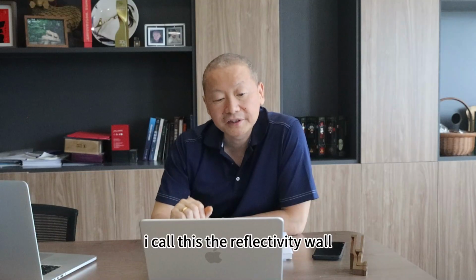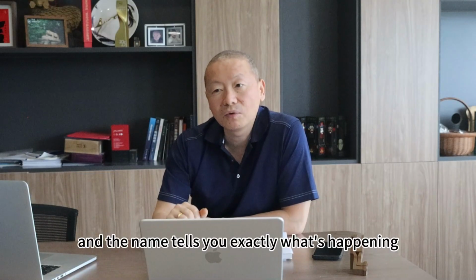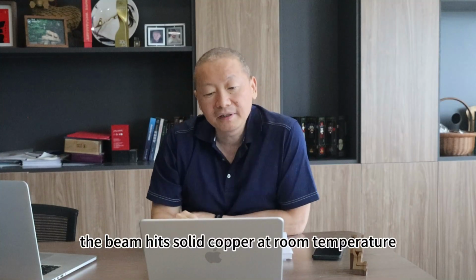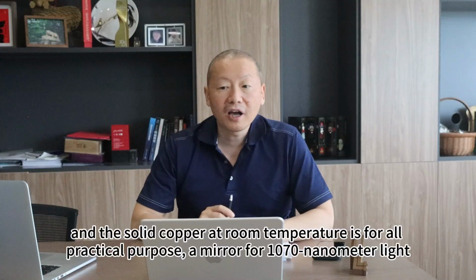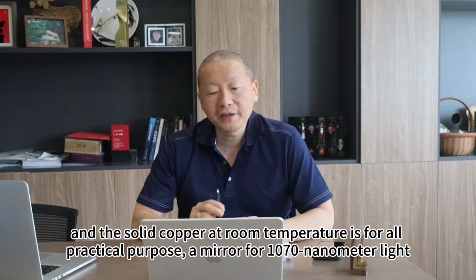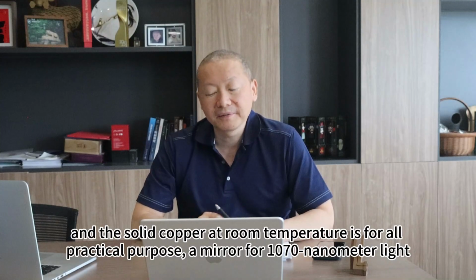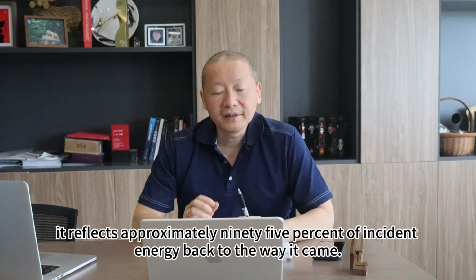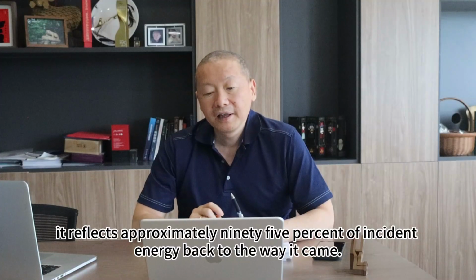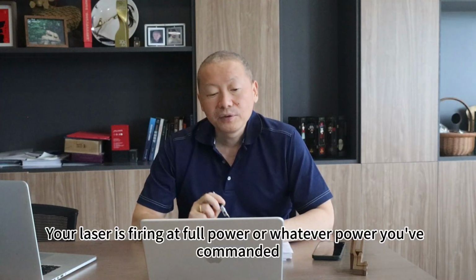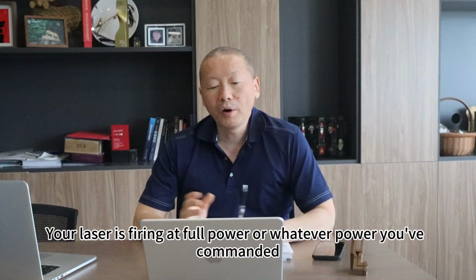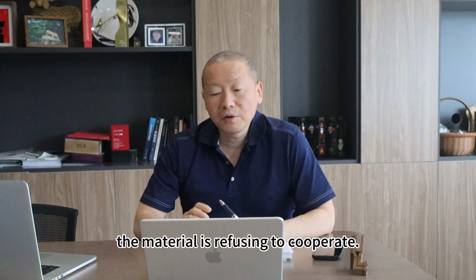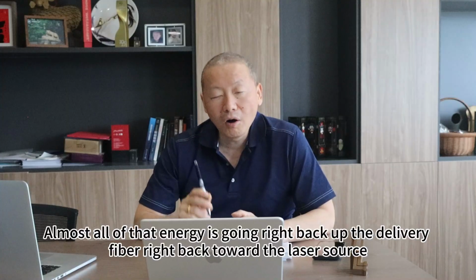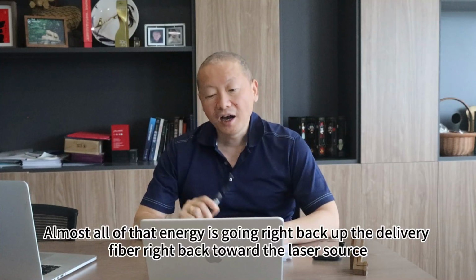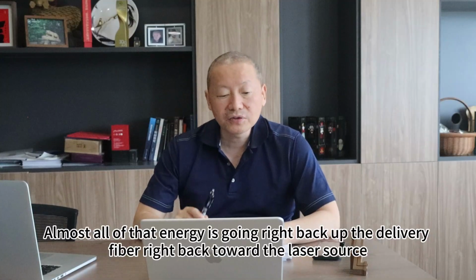I call this the reflectivity wall, and the name tells you exactly what's happening. When your laser fires, the beam hits solid copper at room temperature, and solid copper at room temperature is, for all practical purposes, a mirror for a 1 micron laser. It reflects approximately 95% of the incident energy back the way it came. Your laser is firing at full power, or whatever power you commanded. The material is refusing to cooperate. Almost all of that energy is going right back up the delivery fiber, right back toward your laser source.